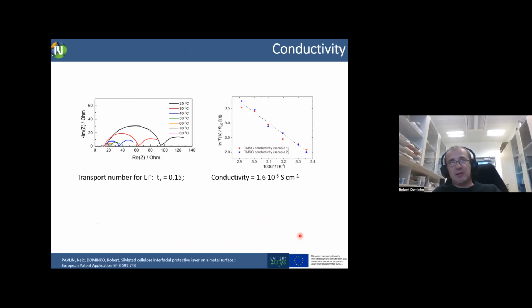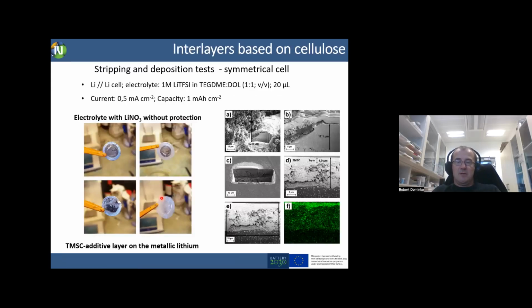And that gives us a possibility, this more or less constant layer gave us a possibility to also measure the conductivity of the layer, which is reported here. It's 2 orders of magnitude lower compared to the liquid electrolyte. And also transference is quite low, and that's why we now have activities going into all solid state batteries by using polymers, single ion conductive polymers inside, which can improve the conductivity, which can also improve the resistivity of the interlayer.